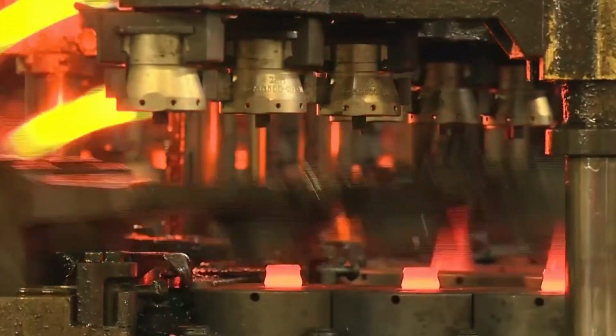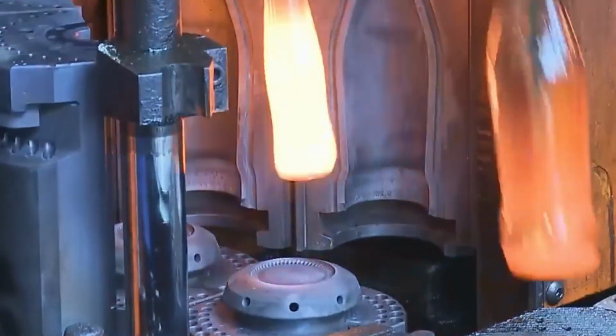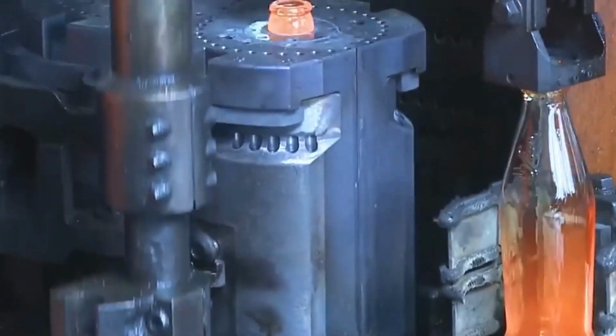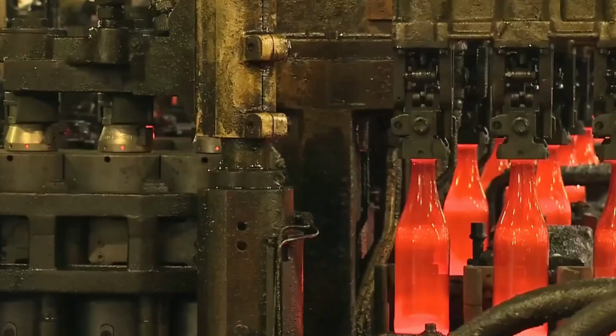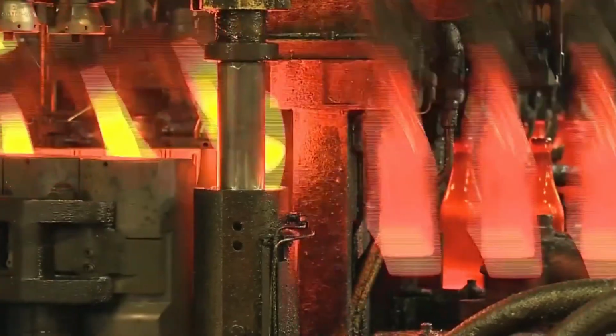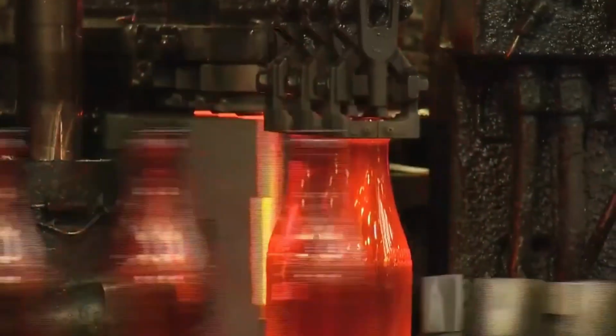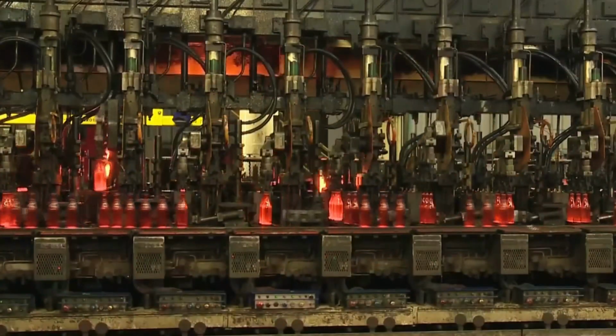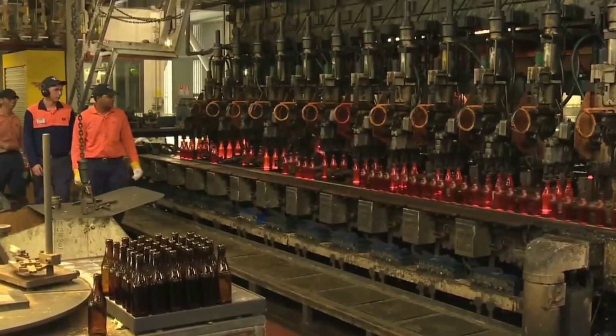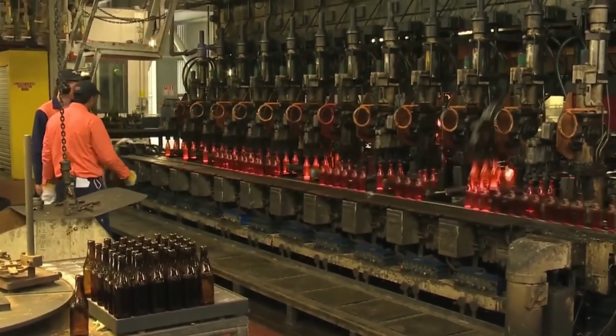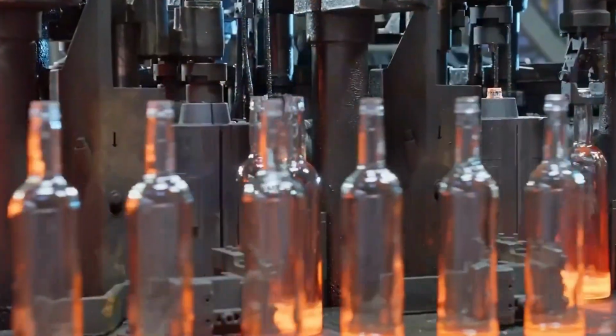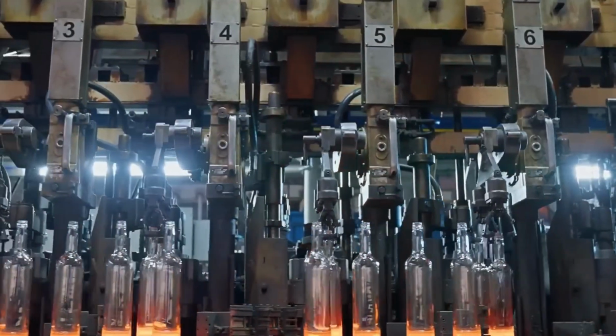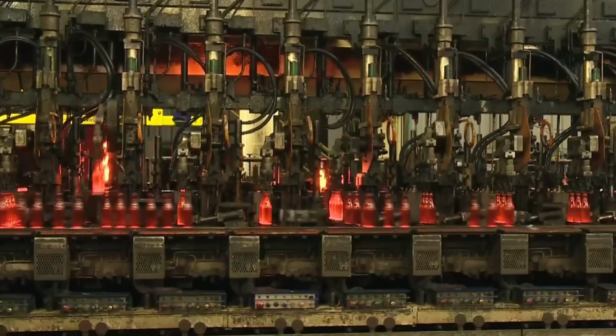But here's the scary part. Each bottle looks solid now, but it's still full of internal stress. Fresh bottles enter the annealing tunnel. Temperature drops slowly from 500 degrees Celsius to 400 degrees over 20 to 30 minutes, relieving internal stress. If annealing is skipped or rushed, internal stress remains and bottles crack during filling. A bottle that passes forming but fails annealing can shatter in a customer's hand.